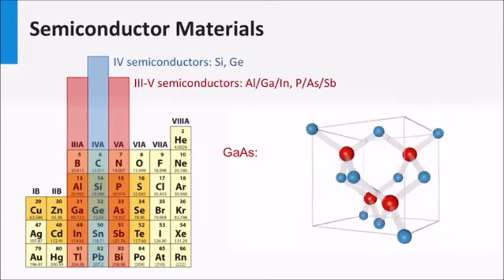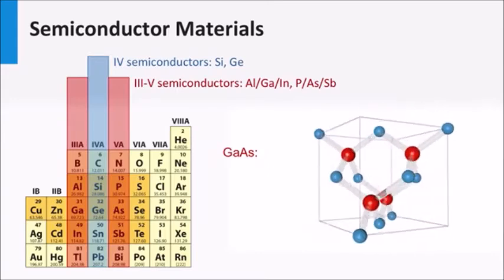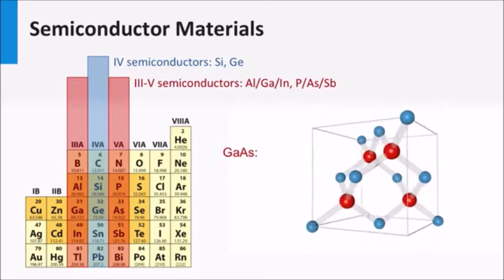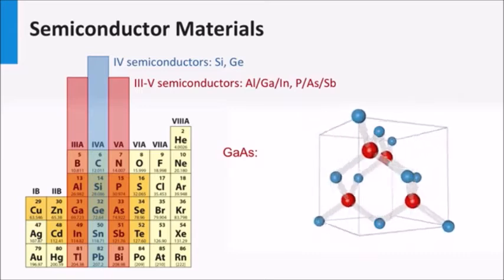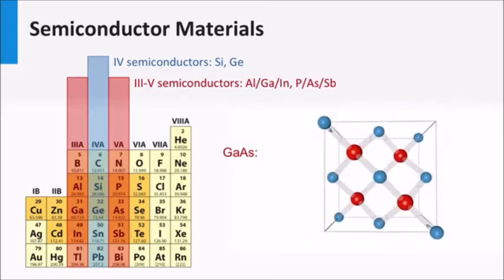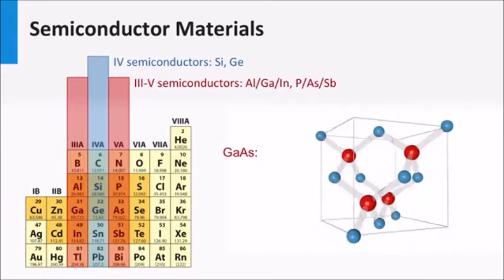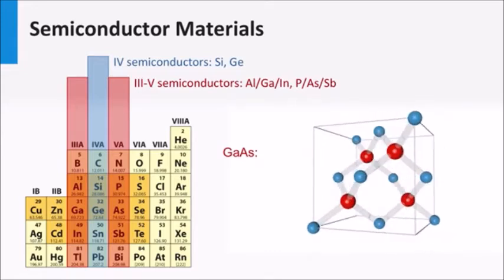Materials with semiconductor properties can be made from other materials than elements with 4 valence electrons. Let's consider the so-called 3-5 semiconductor materials, like gallium arsenide. A 3-5 semiconductor consists of 2 elements. One element has 3 valence electrons, the other element has 5 valence electrons. These materials can, similar to silicon, form a diamond cubic crystalline lattice.